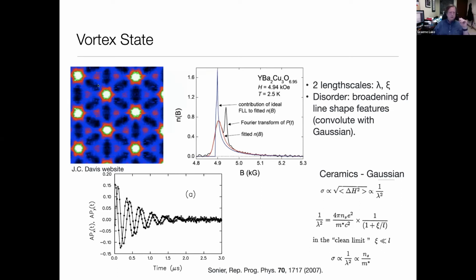In MuSR, we implant muons which land randomly throughout the vortex lattice. And so they experience the magnetic field in different regions, and they sample the whole field distribution. If the muons land near a vortex core, they see a large field and they precess quickly. If they're well away from the vortex core, they see a smaller field, and so they precess more slowly. And so they dephase, and this gives a damping of the polarization. If we Fourier transform this signal, you see a minimum field that occurs, for example, in the center of the triangular lattice, farthest away from the vortices. There's a maximum field, which is at the vortex core, which gives you a high field cutoff. And there's a most likely field, which is along this boundary in here. And so from that, you get a classic line shape. From that, you can directly measure the penetration depth and the coherence length.